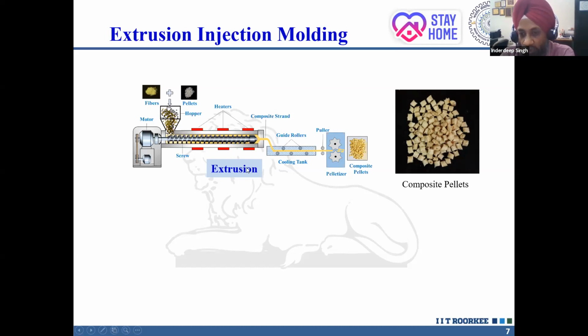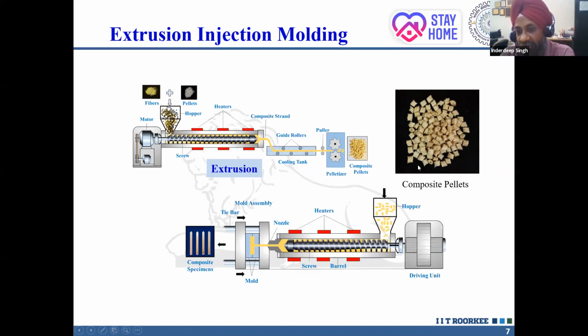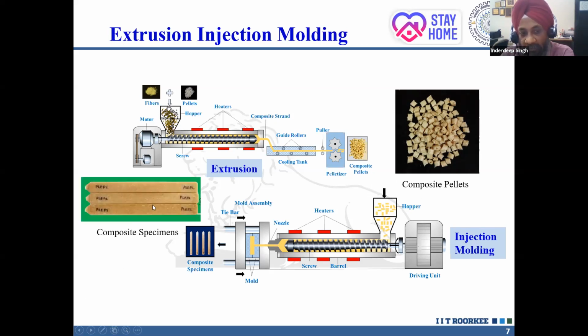So once you get these composite pellets, these pellets can then be used as the raw material for the injection molding machine. So this is injection molding. Therefore, the name of the process is extrusion injection molding. So first we extrude the composite pellets by compounding the fiber and the polymer, and then we injection mold the composite pellets into the specimen. So what kind of specimen? These are the specimens that we are able to make.